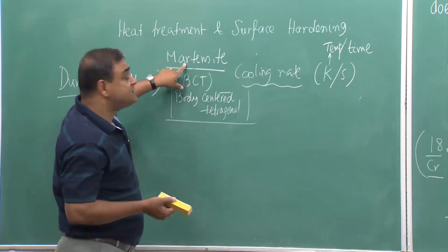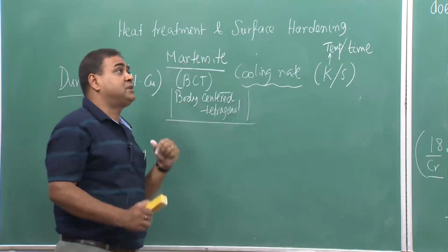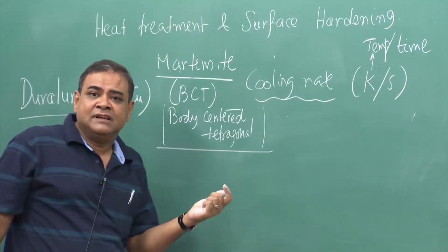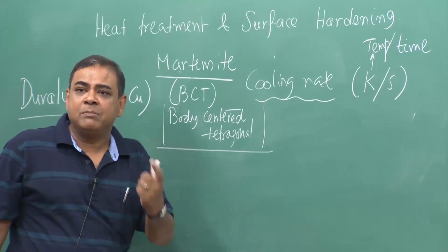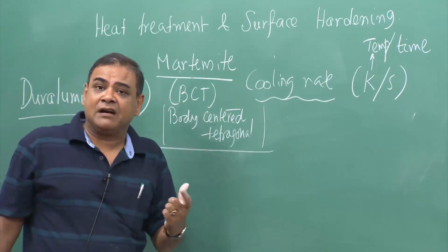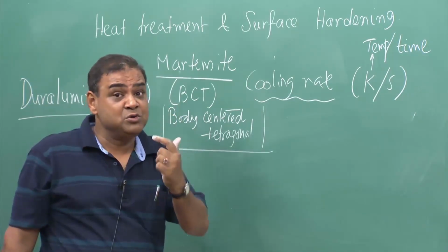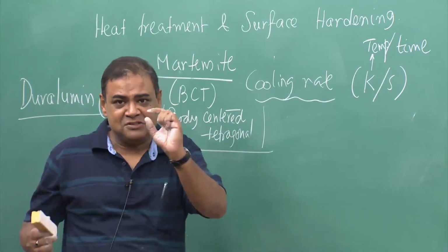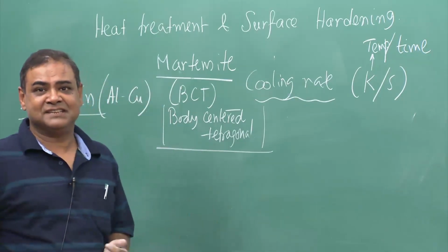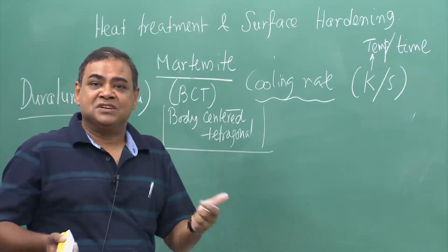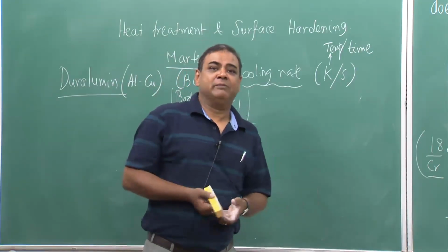But if we take this martensite to a little higher temperature, around 500 degrees Celsius, the martensite tempers and forms a phase called tempered martensite. At that time it incorporates a little bit of ductility. Of course, the strength reduces a bit. It does not reduce much, but its ductility enhances. So, you can incorporate these properties into a cutting tool, so that we can have a longer performance.